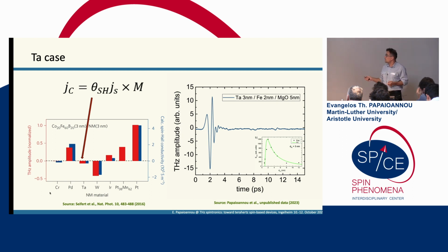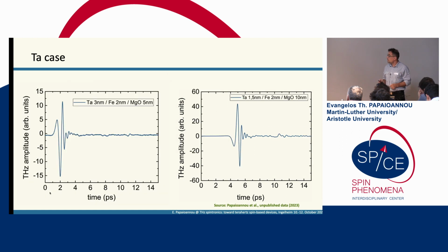We have shown this in iron platinum. Many people have seen this thickness dependence of the signal. However, we get a small signal for tantalum. But when we went to thinner tantalum layers, we saw a drastic increase of the signal. And this was a kind of a trigger for doing more research on it. So the tantalum 1.5 nanometers, iron 2 nanometers gave us 3-4 times higher signal than was expected.